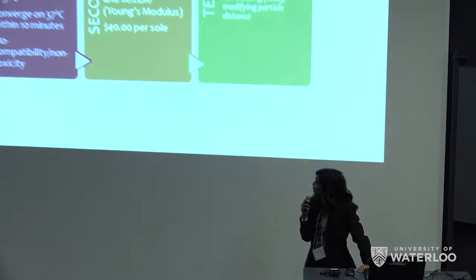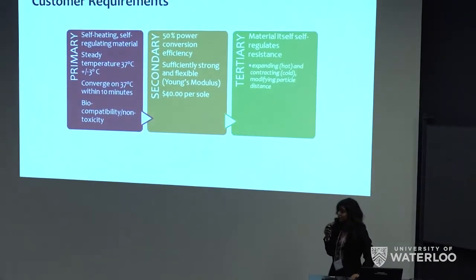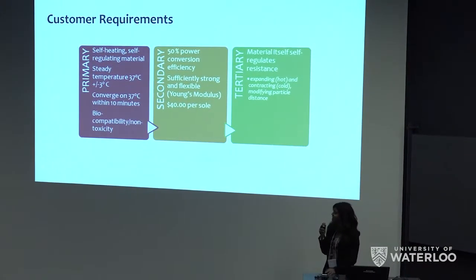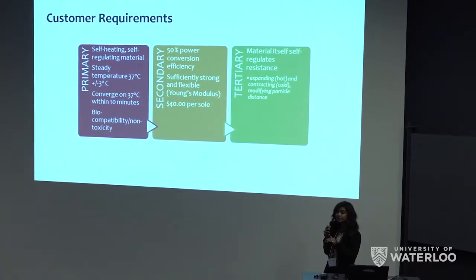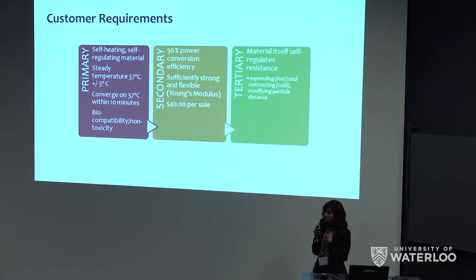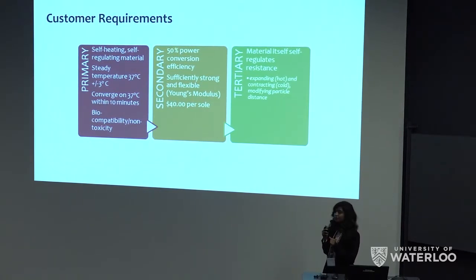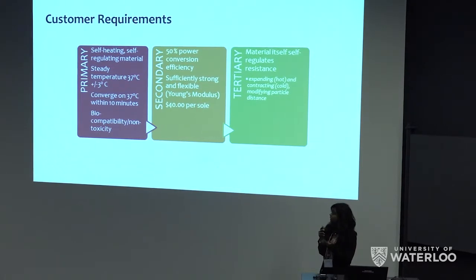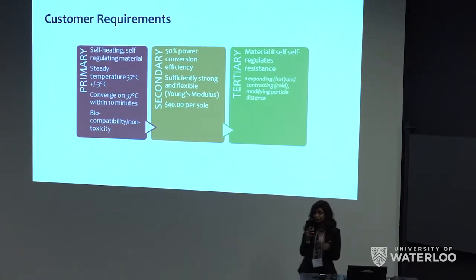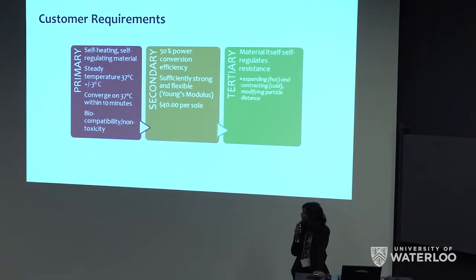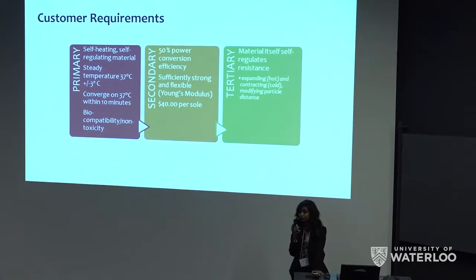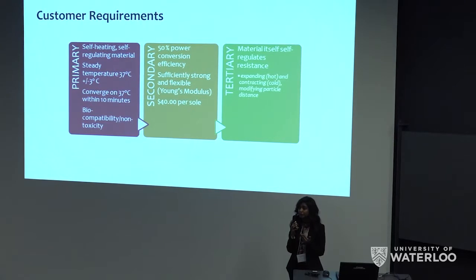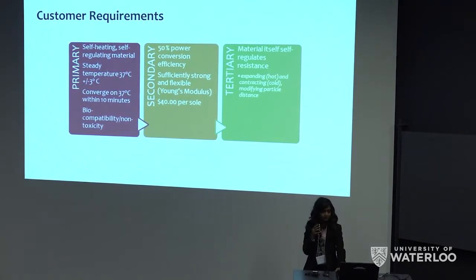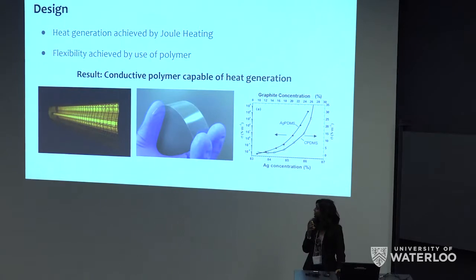I'm going to talk a little about the customer requirements, focusing mainly on the primary requirement. The first requirement is to develop a self-heating, self-regulating material. The second is to ensure that a steady temperature is held at 37 degrees Celsius, with convergence on 37 degrees Celsius within 10 minutes of fluctuation in the external environment. In addition, biocompatibility and non-toxicity are very important for our device, given that it's in very close contact with skin. We're going to move on to engineering design.